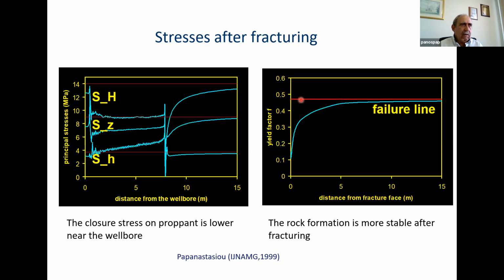Now you can see, before fracturing, the stress state is very close to failure. Now, if we do hydraulic fracturing and allow the fracture to close on the proppant, we push the stresses away from failure. Here, basically, we are just on the fracture surface. You can see that the stresses move far away from the failure line as we move to the distance perpendicular to the fracture surface. So far away, it's like not seeing the hydraulic fracture. But very close to the fracture, we push the formation away from failure.